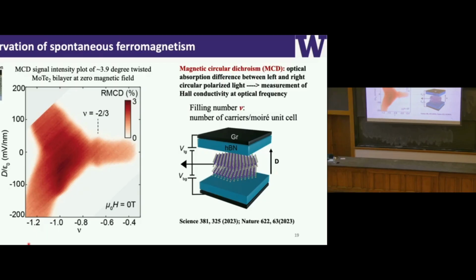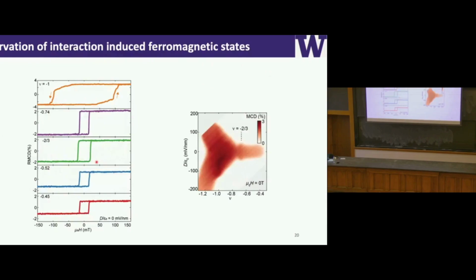Within this phase map, I can already see something interesting. At a fractional filling, for example 2/3, we see there's a little kink feature. That already indicates there's a state underneath this ferromagnetism. Usually when you see circular dichroism, it's an indication of ferromagnetism, but it doesn't prove it. For example, we know sugar molecules can also give you circular dichroism, but a sugar molecule is not a ferromagnet. So to prove you have ferromagnetism, you have to measure the magnetic field dependence and show the hysteresis effect.